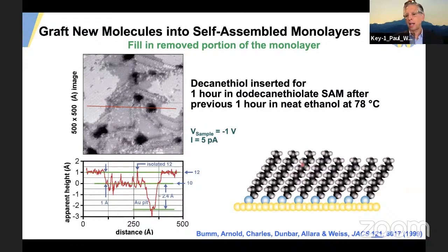in which we use these saturated alkane thiol chains in combinations of different lengths, measured with STM in the identical structures. So for instance, it was known that here where there are 2 more CH2 groups in this one versus that one, that the physical height difference is 2 angstroms. And in our STM measurements under these particular conditions, we get a 1 angstrom height difference. There was a concern that there might be cooperative effects, so we controlled the assembly such that we had domains of the longer chain, domains of the shorter chain, and then isolated molecules of the shorter and the longer in the longer and the shorter domains. And it turned out there were not cooperative effects.